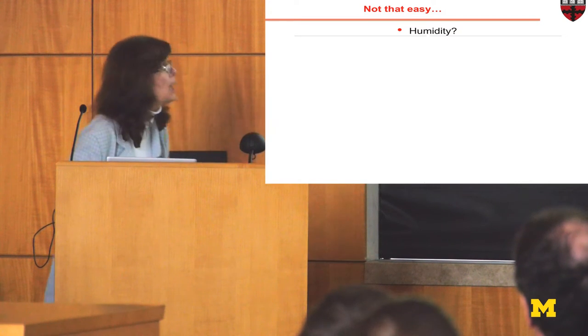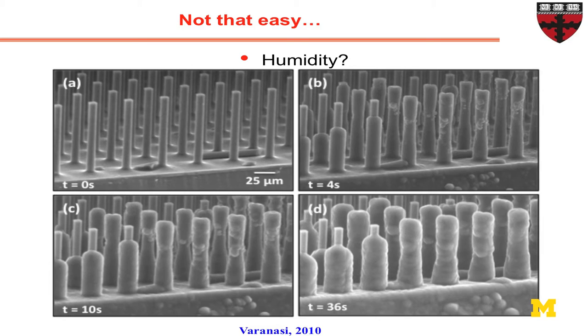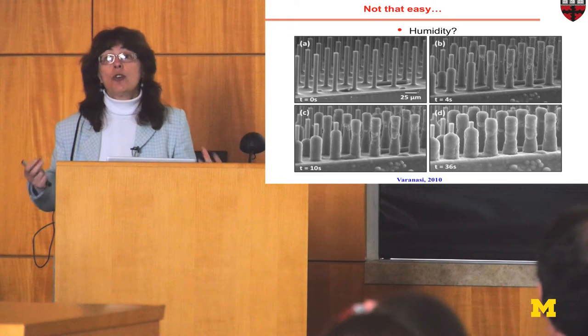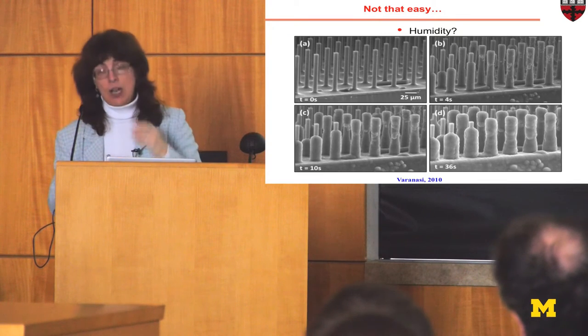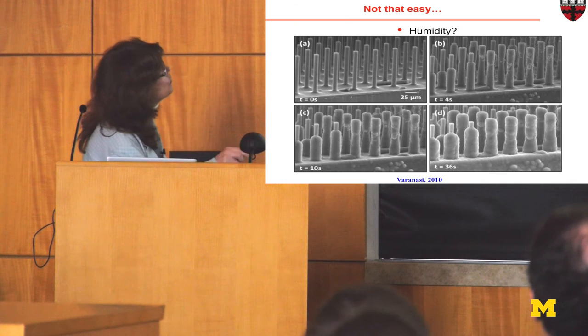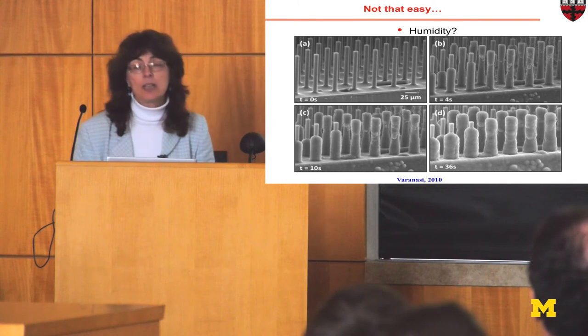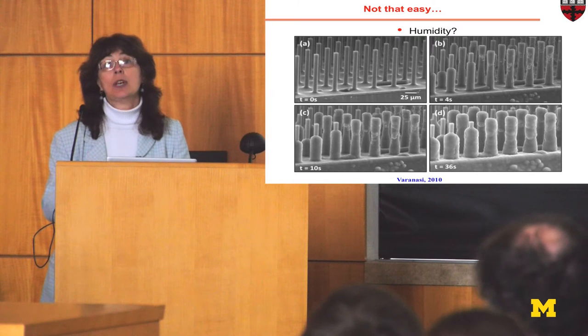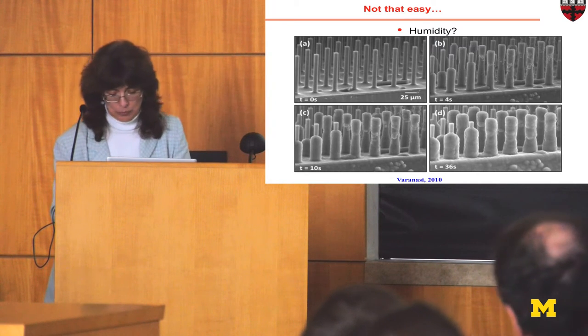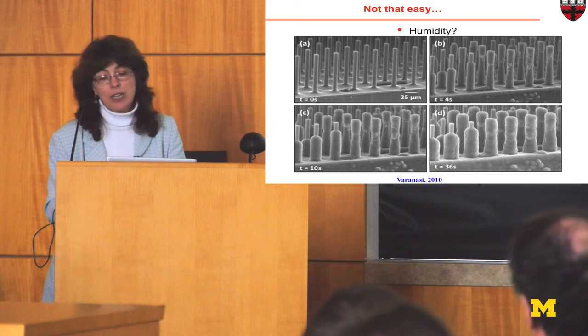And when humidity goes up, and there are many more papers on this subject, including Varanasi's paper, these superhydrophobic surfaces actually behave worse than a flat surface, because it's not about ice anymore, it's about condensation on the surface, it's about nucleation, and now we have even more surface for nucleation. So if it's about frost, which is a high humidity process, then you begin to form ice all over the place. So instead of being ice repellent, it provides even higher adhesion than a regular surface.